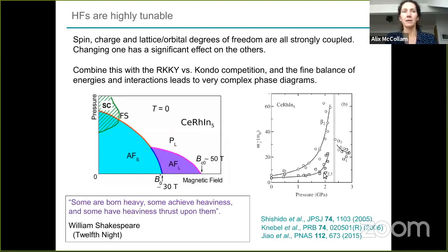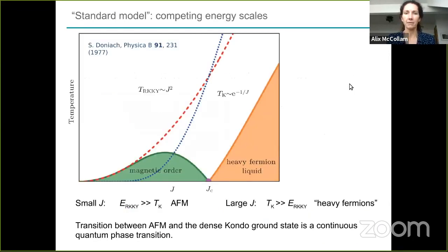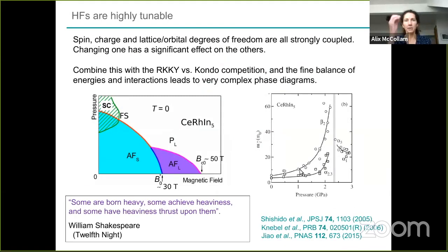In reality, the heavy fermion systems are highly tunable. This phase diagram, it's relatively easy to get across it. If you start somewhere here with magnetic order, it's not that difficult in the heavy fermion systems to suppress the magnetic order and move to some other region of the phase space. High pressure is a very strong tuning parameter. Magnetic field, of course, is what I will be talking about primarily, but chemical doping is also a way of affecting this Kondo coupling and moving yourself across this phase diagram. It's particularly influential on all of the properties of the materials, because in these correlated electron systems, all of these degrees of freedom are very strongly coupled. So if you modify one, you're changing the others quite a lot.